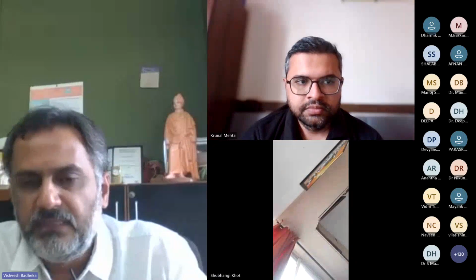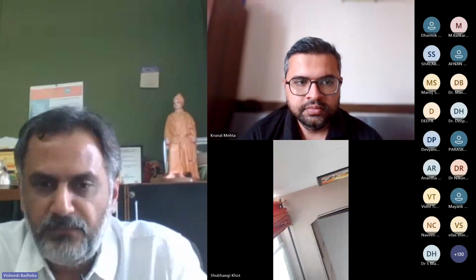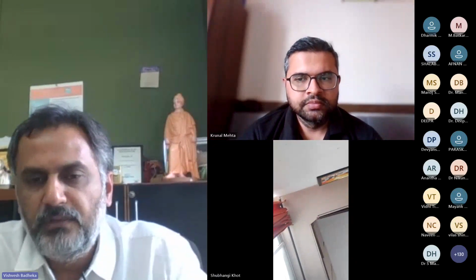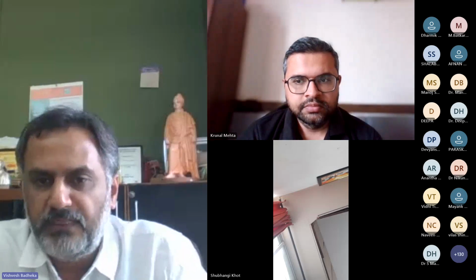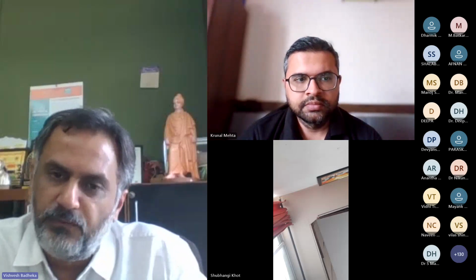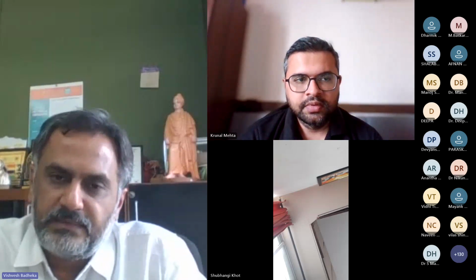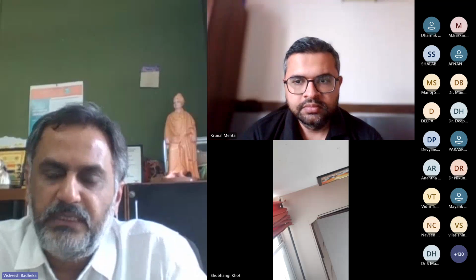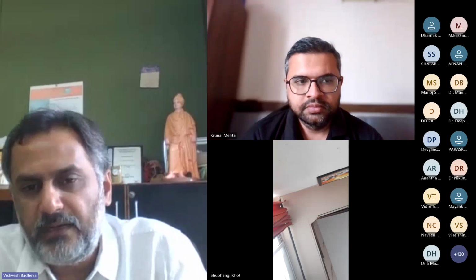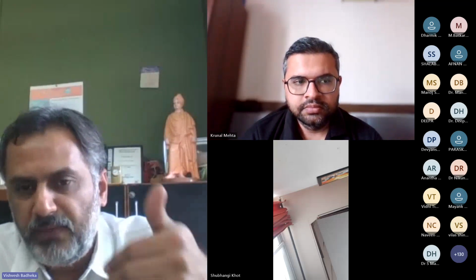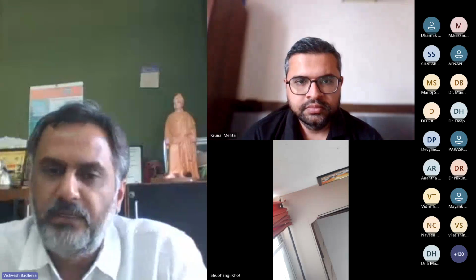If they are of the same material, say for example aluminum and aluminum, and only the difference is in the thickness, then the one with the higher thickness will go on the advancing side of the tool, and the other one will go on the retreating side of the tool. So when you have different thicknesses of the same material, the higher thickness goes on the advancing side, and the other comes on the retreating side.